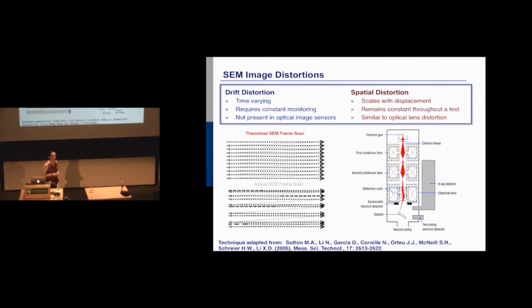So that was the first challenge. We got over that hump. The next problem was actually distortions in the scanning electron microscope. If you're doing this approach on the macro scale, you take your specimen, you take a camera, and you take images. Boom, boom, boom. And all the pixels are taken at the same time. You take an image, you collect everything at the same time. There's going to be a parametric distortion to your lens, just like your glasses lens. If you look through the center of your glasses, it's not distorted. But if you look off to the side, there's a distortion. It's the same in a camera lens. That's very easy to correct for. It's very parametric. You can establish it and correct for it, and it doesn't really change.